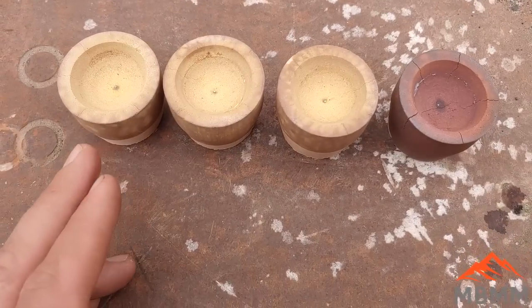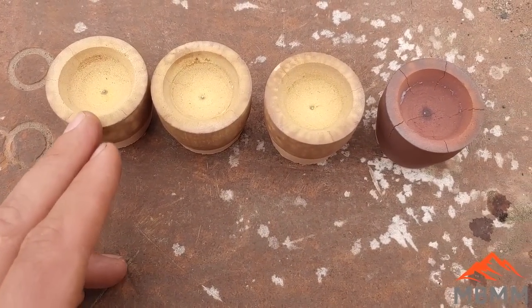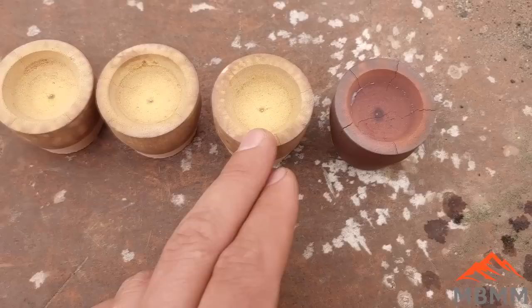Also, with copper in particular, if you have a lot of copper, those copper oxides bring precious metals with them as they go into the cupel. Not a bunch, maybe 5% of your total button. But it's certainly enough when you're talking about assaying or getting really accurate. You want to be aware of copper and nickel in particular. So here are our beads from our tailings, 50 plus, 50 to 100, and 100 minus.